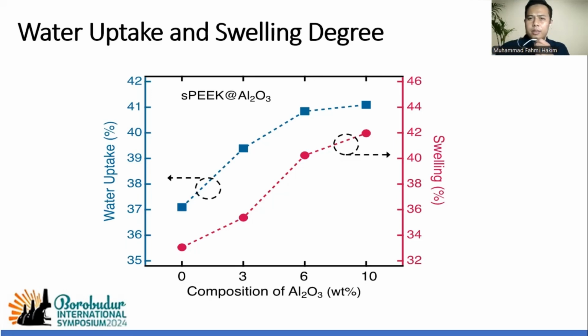High water uptake value indicates a high membrane conductivity. Therefore, the membrane will be excellent for DMFC application. And same with the swelling degree. The swelling degree and water uptake are not too different. And then we must know the cause of water absorption in the membranes and prevent excessive absorption, a condition that might lead to instability in the membranes.